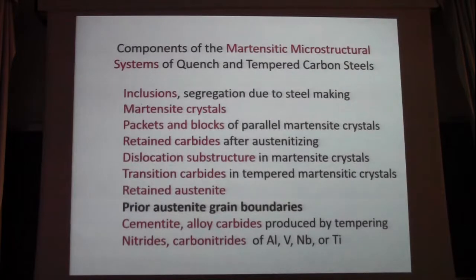So steels are processed, then they're austenitized, and then they are quenched, and then finally they are tempered. So the martensite crystals, in low and medium carbon steels, are extremely fine. They are small, and they occur parallel one to the other in the microstructures. Another important thing, because we austenitize, what happens during austenitizing is critical. We don't make 100% austenite. There are carbides, and certainly the inclusions don't go away, but some carbides are retained, and they influence fracture, especially ductile fracture.